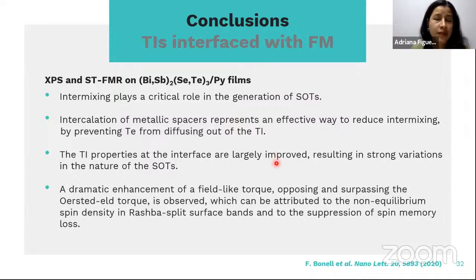I just want to quickly give you some take-home messages on this part. It's important to let you know that in the case of TIs interfaced with permalloy, intermixing plays a critical role in the generation of spin orbit torques, and the properties of the topological insulators are largely improved when we place an interlayer. Because of the introduction of such an interlayer, we can also have a strong variation in the nature of the spin orbit torque, so that we can have an enhancement of the field-like torque at the interface, which is relevant for spintronic applications.